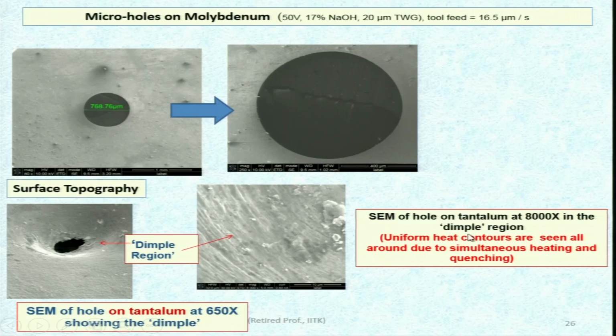SEM of hole on tantalum at 8000 magnification. Uniform heat contours are seen all around due to simultaneous heating and quenching. These are the uniform heatings, and the region shows simultaneous heating as well as cooling, because cooling is taking place simultaneously, since it is immersed in the electrolyte.